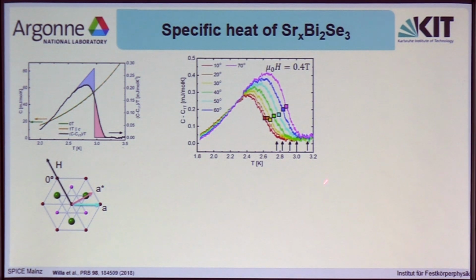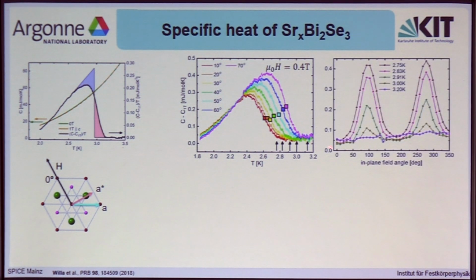So now there's two ways of looking at this. We could either take cuts for constant temperatures through these different field angle sweeps, and I'm plotting this here on the right. So you can see here the in-plane field angle and the specific heat for different temperatures. What you see here for high temperatures above the superconducting transition, the specific heat is essentially constant, whereas once we start entering the superconducting transition, we see a clear twofold anisotropy of the specific heat emerging.